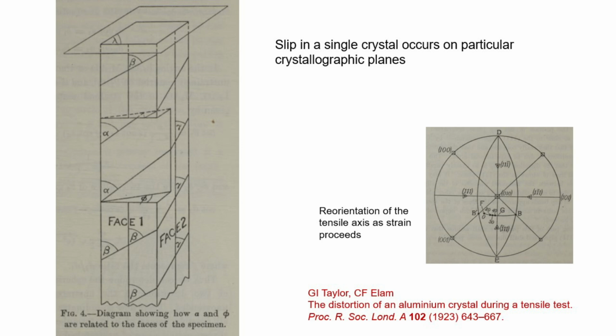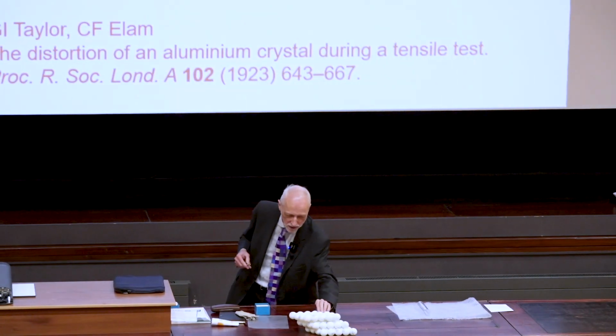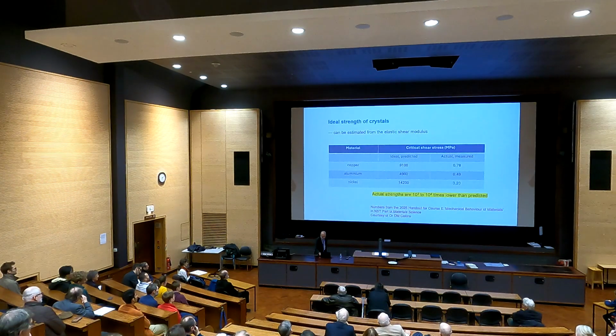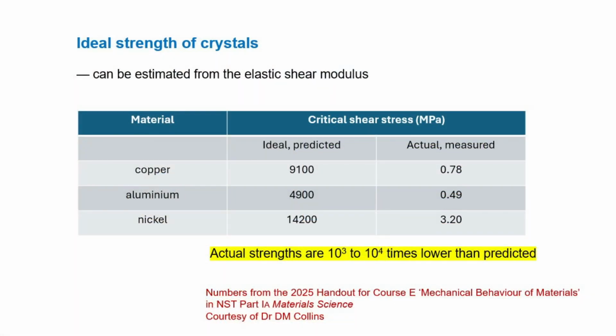So from this work, we have a really secure understanding of what it is that is moving in the single crystal when it deforms. There is, however, a problem, and it's a pretty big problem. That is, if I take a crystal and I stay in the elastic regime, I can push it a little bit, and it'll have a resistance to that, and I can measure that as an elastic modulus. It will then just spring back. But the value of that elastic modulus should be a pretty good guide to how hard I have to push to get the plane to actually move irreversibly. And when you do that calculation, you get a set of predicted strengths, if you like. And here they are in megapascals. And when you measure the strength, these are the values you get.